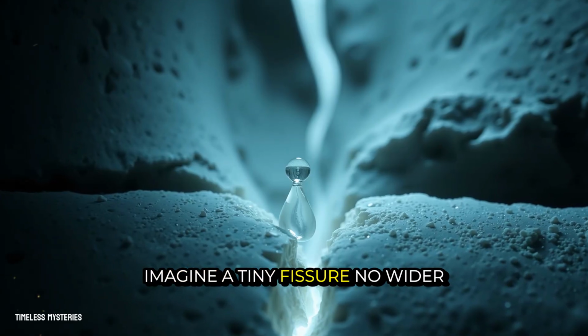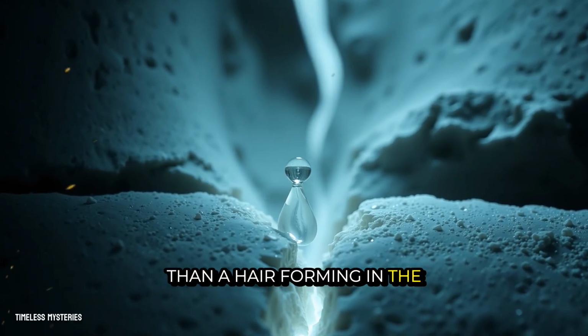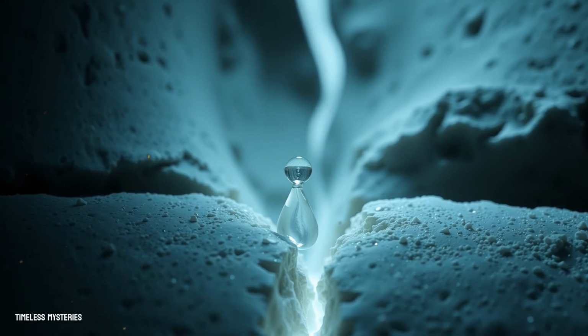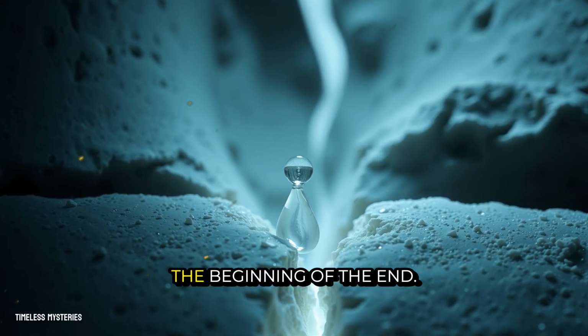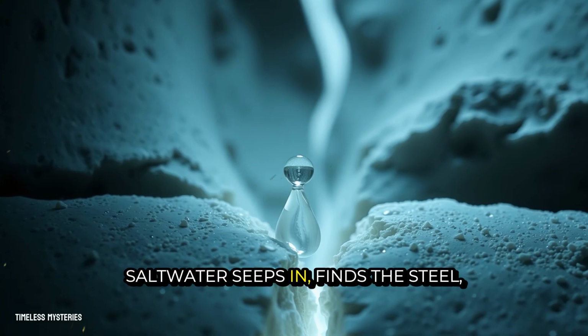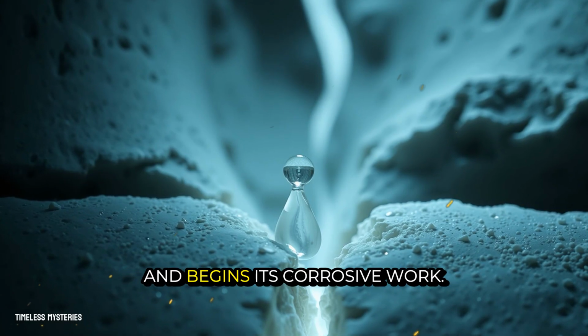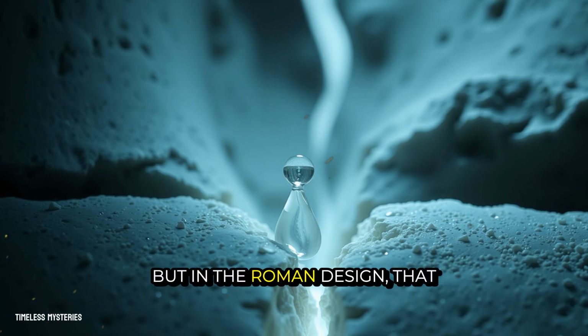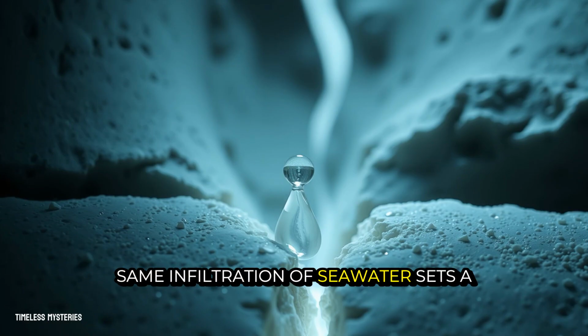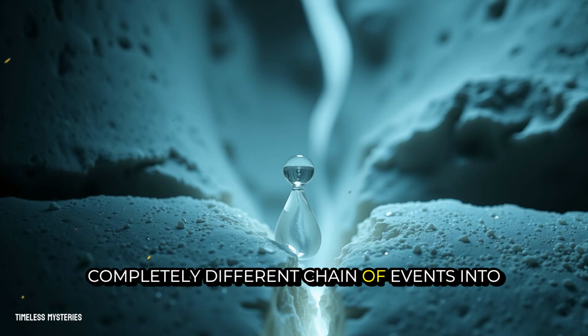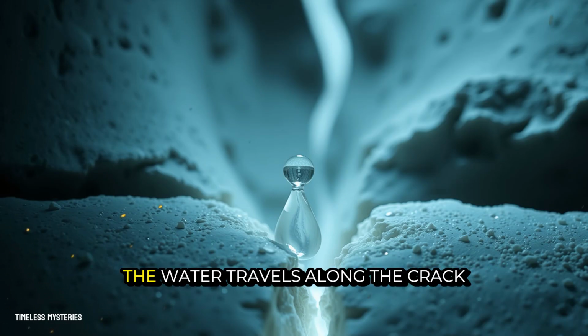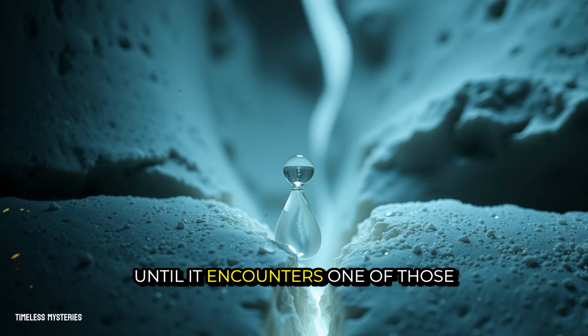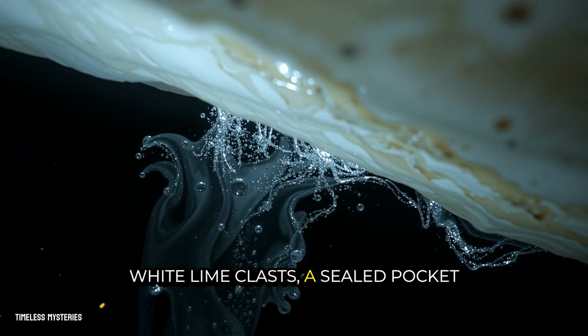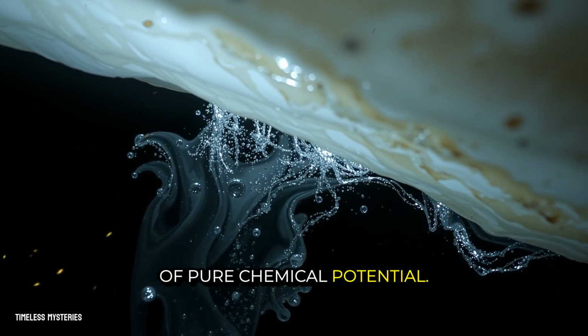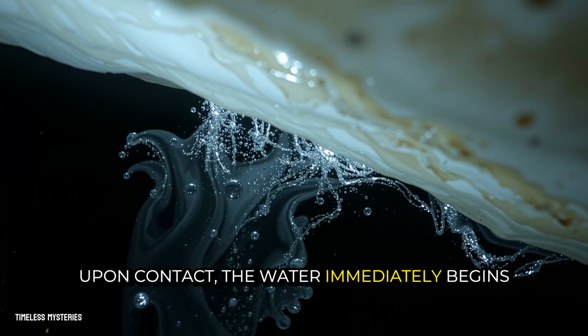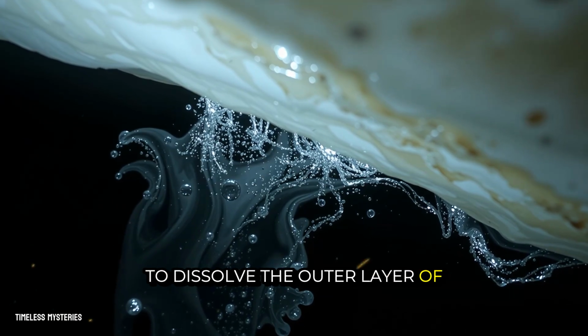Imagine a tiny fissure, no wider than a hair, forming in the concrete after centuries of pressure. In any modern structure, this is the beginning of the end. Salt water seeps in, finds the steel, and begins its corrosive work. But in the Roman design, that same infiltration of seawater sets a completely different chain of events into motion. The water travels along the crack until it encounters one of those white lime clasts, a sealed pocket of pure chemical potential. Upon contact, the water immediately begins to dissolve the outer layer of the clast.